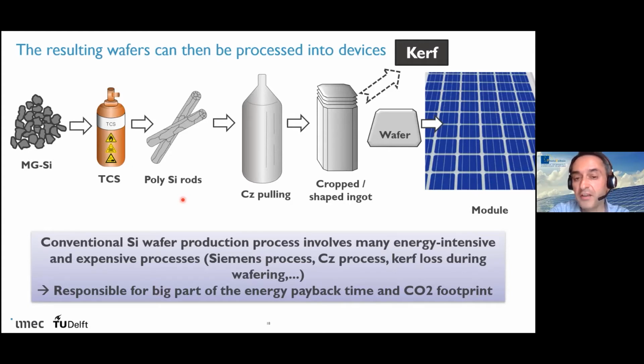To give you an idea, the energy payback time for a silicon PV module at the moment is around 1 year. Of course it depends on where you use it, but it means the amount of energy needed to create the silicon PV module is generated again by the module after 1 year. And of course you can use a PV module much longer, 20, 30 years, so you will produce much more energy than you needed to put in. But a lot of the energy needed to make the module actually comes from making the wafers.